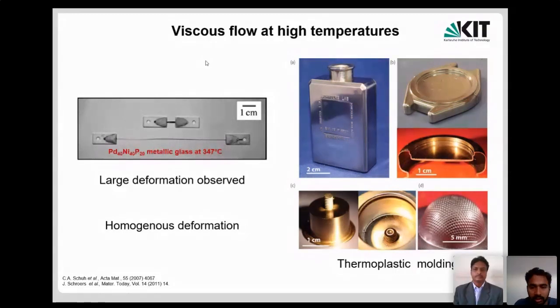It depends on what application you want to use it for. If you are using it for biomedical applications, normally people go for titanium-based alloys, so you go for titanium-based metallic glasses. But if you are looking for strength in the material, then I would go for something like iron-based glasses. But although the iron-based glasses have strength, they are very brittle. So if you need some strength and some ductility, then I would go for maybe copper-based or palladium-based glasses, for a little bit of both strength and ductility. So it depends on the application you are looking for, what kind of chemistry you want.